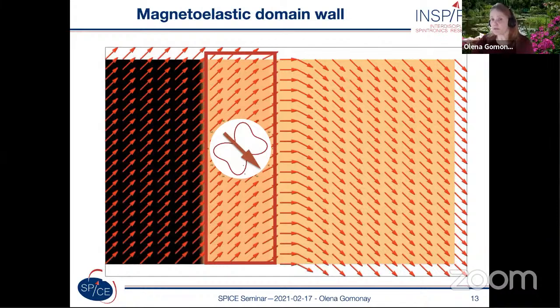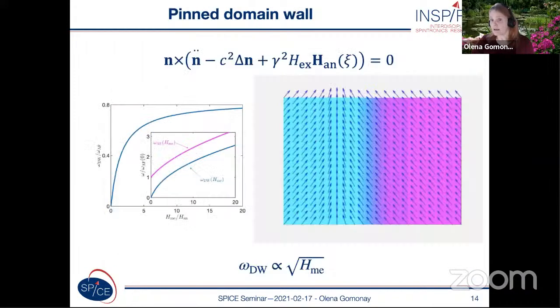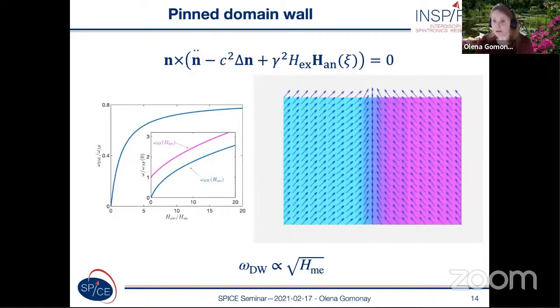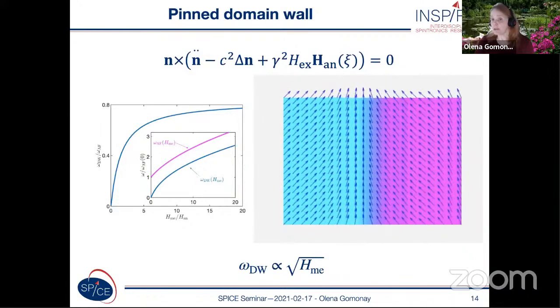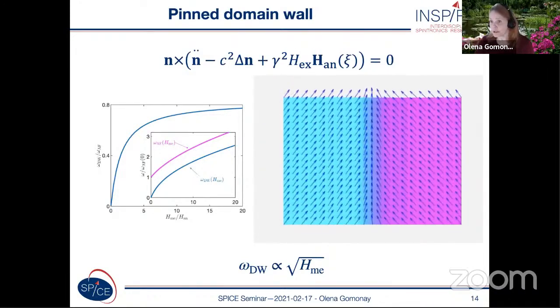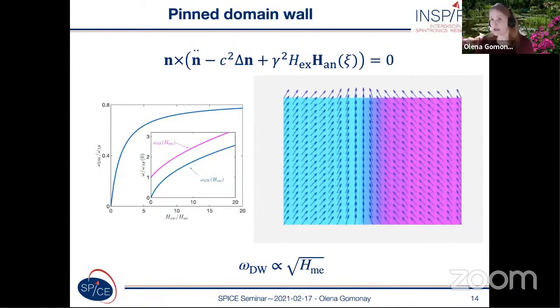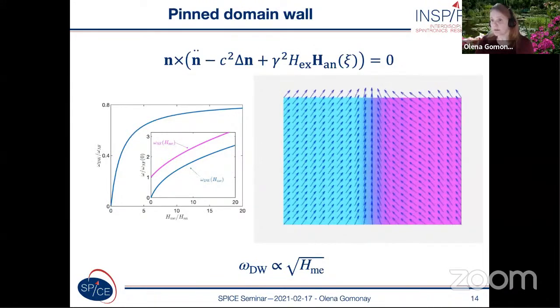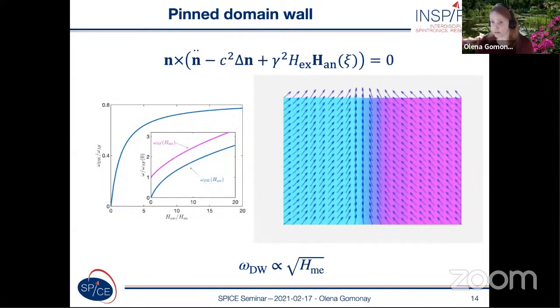So the displacement of the domain wall in this case is associated with an increase of the magnetic energy. And if we look then at the dynamics of the domain wall, we will find that the domain wall is pinned. So if we try to move it, it will oscillate in the vicinity of this magnetoelastic domain wall.